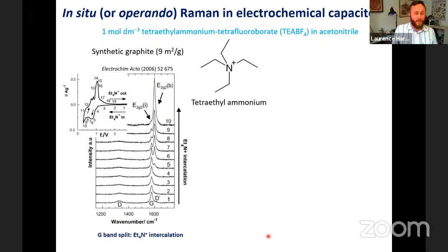So historically, what I've done is look at trying to understand degradation mechanisms within supercapacitor electrolytes. This is a synthetic graphite, so this is not a graphite you'd actually use in a supercapacitor. Note the surface area is extremely small, but it is really to see what reactions are happening as you widen out potentials on very ordered or graphitic portions of the carbon you could be using.